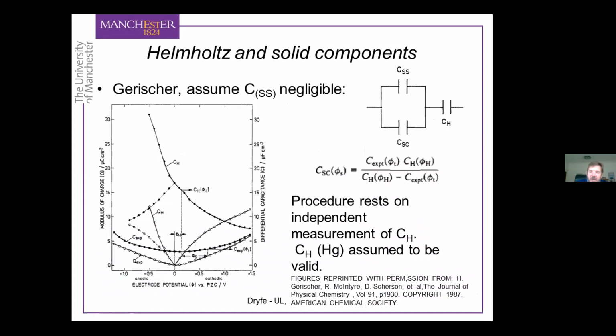So going back to the capacitance model that I said Gerischer developed, by working at a high concentration of electrolyte, he assumed that the capacitance could be considered in terms of only two capacitors in series, the Helmholtz capacitance and the space charge capacitance, which, as I've said, we can't neglect because graphite is a semi-metal. But the question is, obviously, when you do the experiment, you measure these two capacitors in series. So how can you extract these individual capacitance values from the overall experimental capacitance?